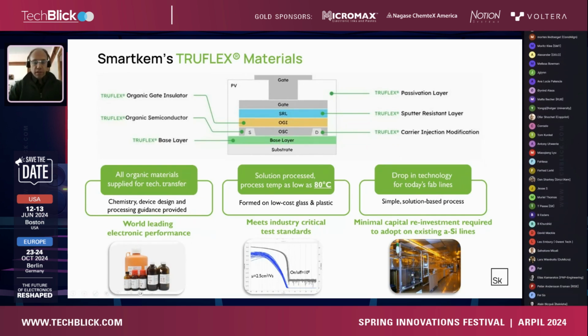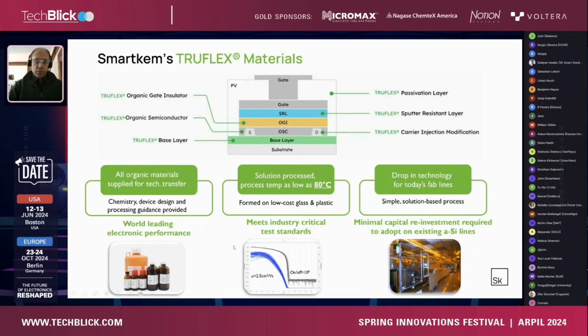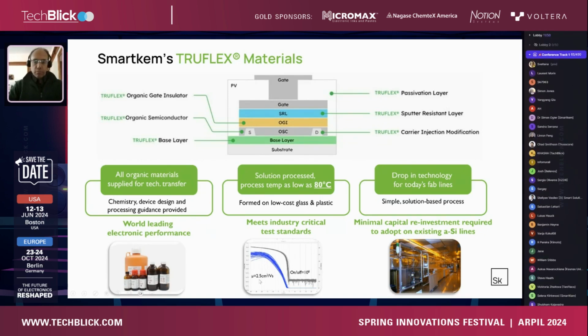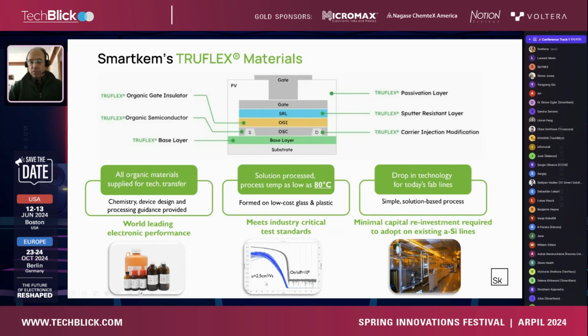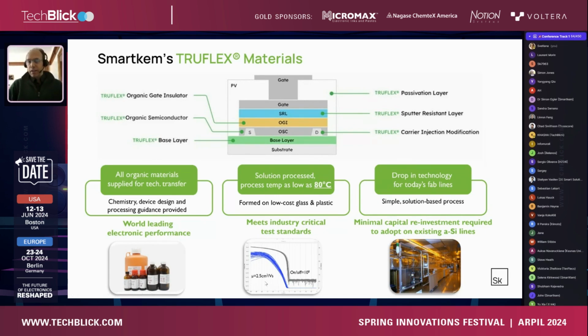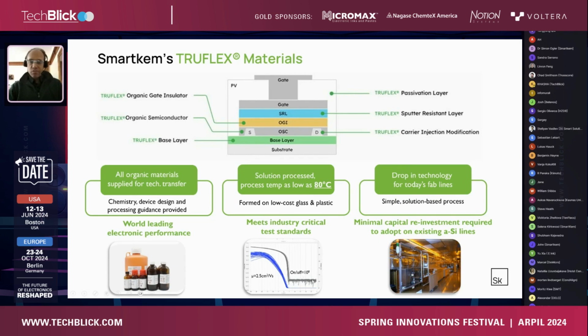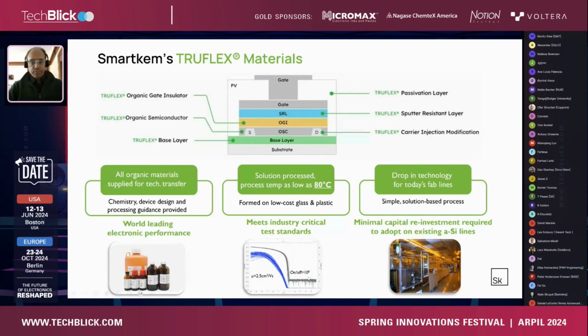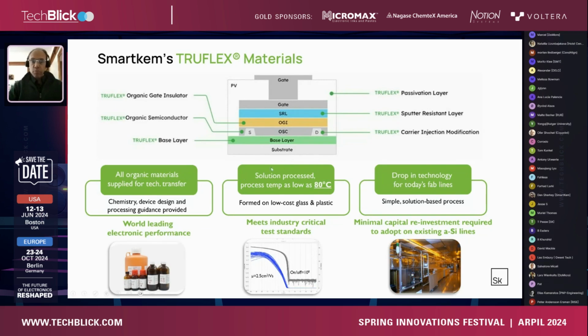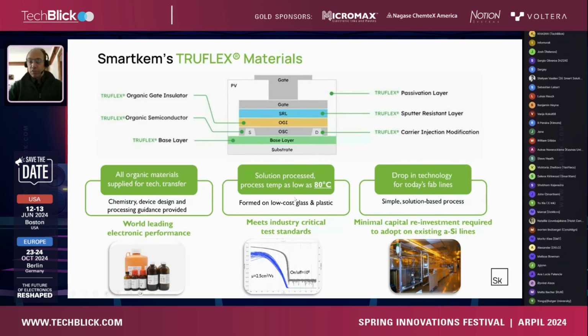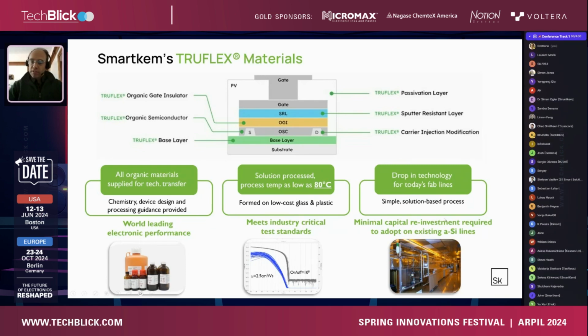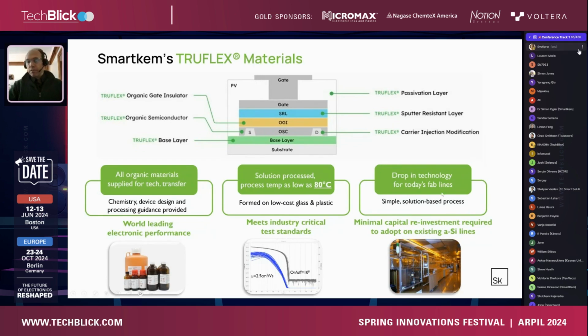So we provide all the materials in a formulated clean room package compatible formulation from sizes from 100 milliliters up to 3.3 liters. All the materials are developed with a high performance, so we have charge mobilities around about 2.5 to 3 centimeters square per volt second at short channel devices. And short channel is typically display industry short channel of 3 or 4 microns. They have high on-off ratio. This is limited by the test system, so the actual on-off ratio is potentially even higher than 10 to the 8. They are low temperature processable materials, and I'll go into more detail about the consequences of that for device applications. And the materials are designed to go on existing amorphous silicon lines. So it's designed to be a drop-in for today's fabrication lines with minimal reinvestments.